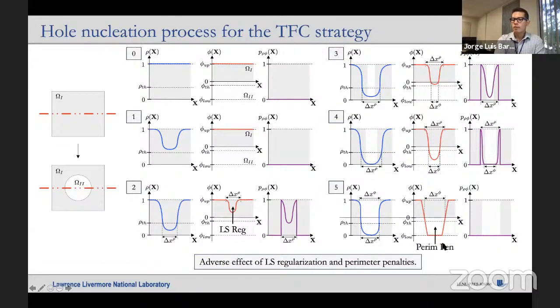Similarly, for the perimeter penalty, when you generate a hole, sometimes the holes are going to be very small. And the penalty will say, hey, you just generated a hole that is not actually contributing much to your problem, you can just remove it to reduce the perimeter penalty. And then your hole seeding is going to be completely annihilated because of this penalty. So the take-home message here is that in order for this two-field coupling to work appropriately, the coupling penalty contributions should be larger than the regularization and the perimeter penalties. That's the take-home message here.